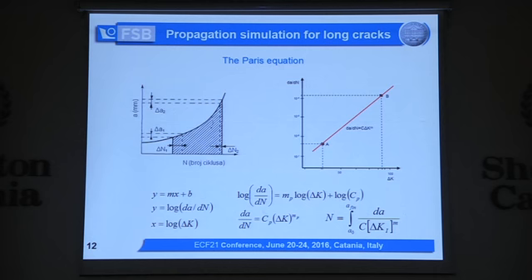And for that we use a power law. A typical power law is the Paris equation. So as you know, in logarithmic scale, in a crack growth rate diagram, da/dN with respect to delta K, we have a straight line, and with some simple mathematics, we come to the Paris equation. This equation is the one which this old man, who is walking around here, produced like 50 years ago. And then we can calculate the number of cycles from this equation in this way here, where we integrate the Paris equation.